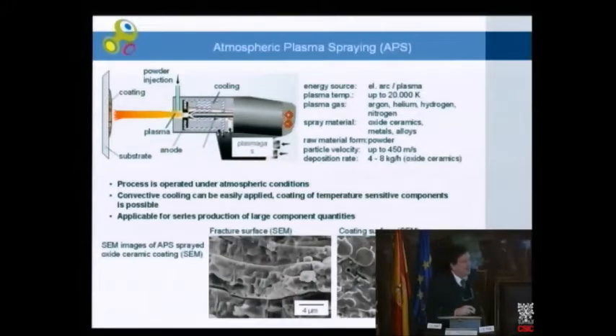What is the main difference? What are the main characteristics between the plasma spraying on one side and the flame spraying, the modern flame spraying techniques on the other side? For sure it is the physical principle, but I do not have the time to go into too much detail on that. The main feature is that with our plasma sources we can achieve temperatures so high that we can melt every type of material, and we can melt it very, very quickly. But we are limited to a certain extent, referring to the efficiency rate, and this means the deposition rate, and we are limited in the kinetic impact, that means the particle velocity, and if we go into more detail, we have to talk about the velocity distribution, the distribution in space, and this means a multi-dimensional approach.